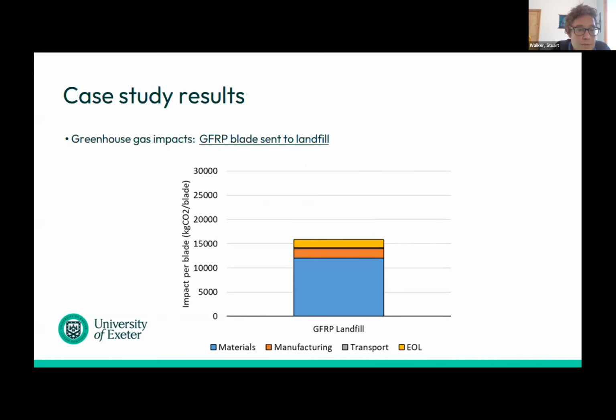And so to move on to some results of the case study. First of all, I have results for glass fiber. This is a glass fiber blade made, used, transported, and then at the end of life is treated by being sent to landfill. You can see there, for the single blade, its total impact is around 15 tons of CO2. You can see that the majority of that is from the materials. There's a small bit from manufacturing. Transport is almost negligible. And then at the end of life, we have a bit of an impact there.